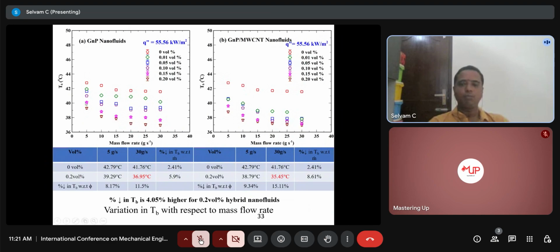But after inclusion of GNP, you can see with respect to the mass flow rate and the concentration, it is significantly reduced. It has been reduced from around 43 to 37, around 36.95 degrees Celsius. This is only for 30 gram per second mass flow rate, and this is only for graphene.